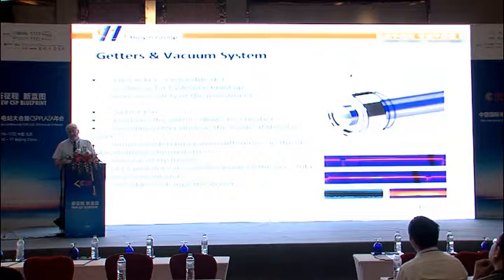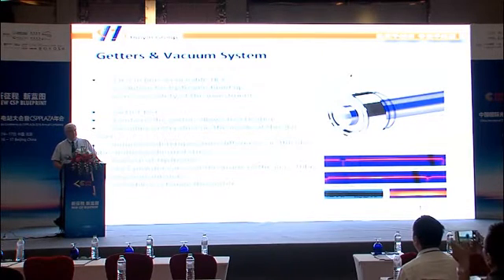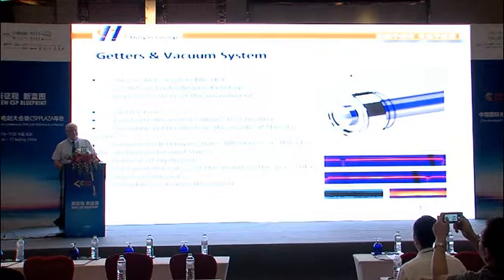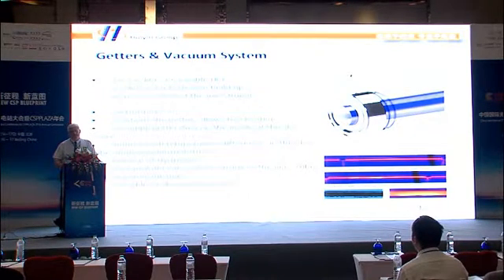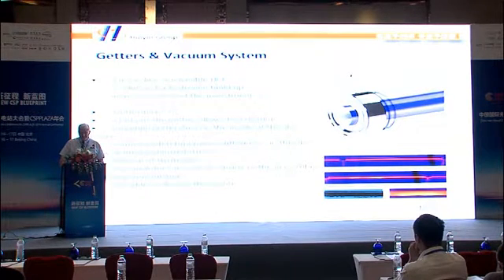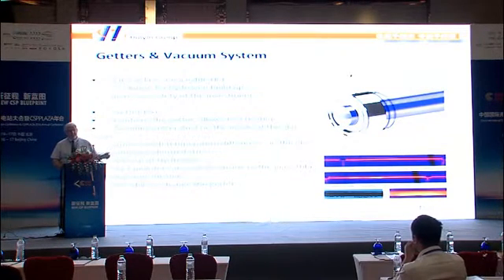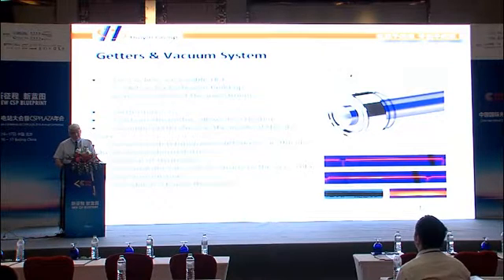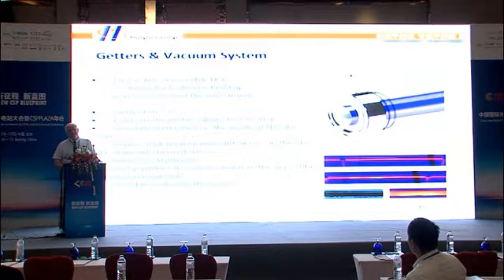Also important, and this is going to be very important for molten salt, are getters and getter dust. Getters are metal powders that are sintered, and once they get saturated, they become like powder. This powder could go into the receiver tubes and fall on the inside of the glass and cause local overheating of the glass tube and cause breakage. And certainly at high temperature, when we have a receiver that operates at 550, this could cause problems.